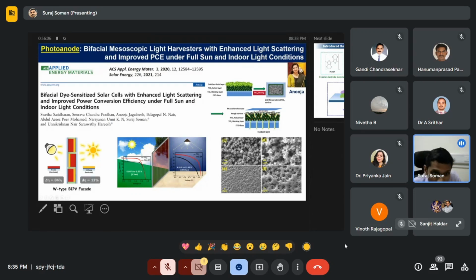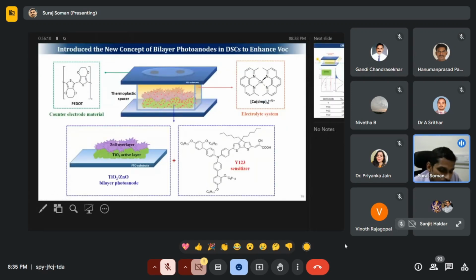And from the back side, around 13% improvement. So this was actually the starting point for something very interesting that happened in our lab, where we came up with a very innovative architecture of bi-layer electrode. So one day, this student Anuja forgot to remove those zinc oxide layer, and she made a solar cell with a titanium dioxide. On top of that, there is a zinc oxide.